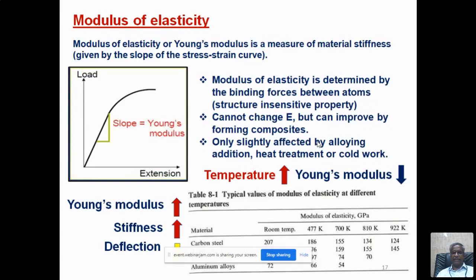Similarly, for any aluminium alloy, the modulus of elasticity, Young's modulus, is something around 70 to 75 gigapascal. It will not vary much, so it is a structure insensitive property. You cannot change Young's modulus, but you can improve it by forming composites. It is only slightly affected by alloy addition, heat treatment or cold work. But temperature will have an effect. If the temperature increases, Young's modulus will decrease. Higher the temperature, the lower the Young's modulus.